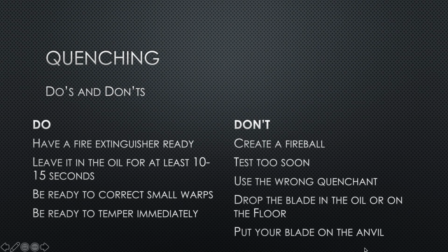So what you shouldn't do, you see this again on Forged in Fire and others, people creating a fireball because they're pulling something out of the oil and it's still hot. If you're creating a fireball, you didn't leave it in the oil long enough. Testing too soon, we talked about this. You've got to let it get through that chemical change. Like the previous slide, using the wrong quenchant. Use the right one. Obviously, don't drop the blade in the oil or on the floor. And the last one, don't put your blade on an anvil. Putting your blade on an anvil, which is cold steel, will make your blade warp. So either hang it, which is the best way, hang it from a hook and clamp it or something, or just try not to lay it down on anything.